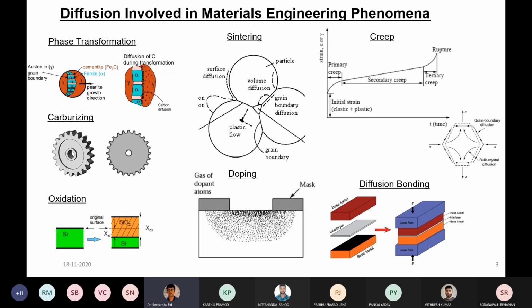This is a very tricky question. You have more vacant places in BCC, but still its capability to dissolve carbon is not so high. But if you look at the FCC phase like austenite, it has a higher capability to dissolve carbon in the lattice. How is it possible? Now, in order to understand that, you have to understand the interstitial positions and what the void shape is.